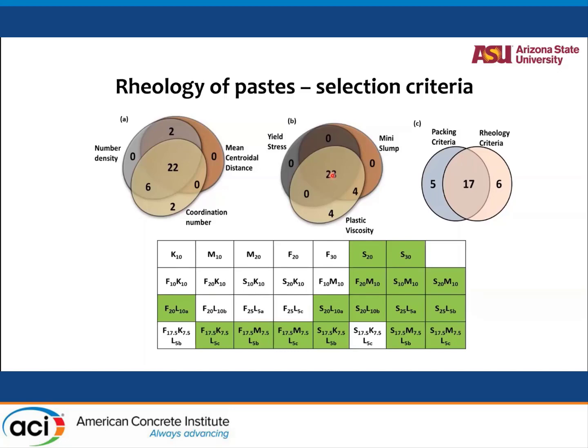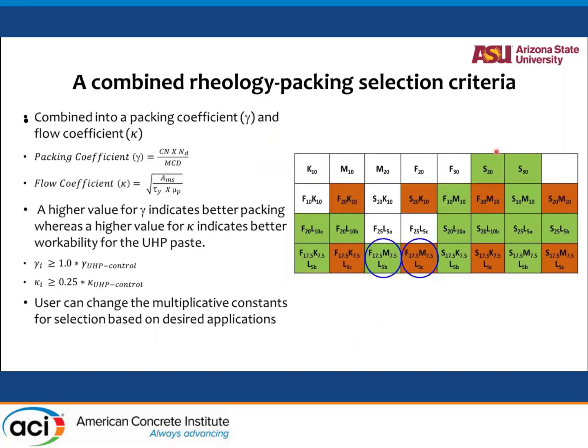And then once you have both packing and rheology combined together, we had 17 mixes out of 32. So about 50% of our mixes satisfied the criteria that we wanted. Like I said, again, it's because we started off with a careful set of materials rather than doing a trial and error approach. So now we said, okay, can we do a combined rheology and packing coefficient?